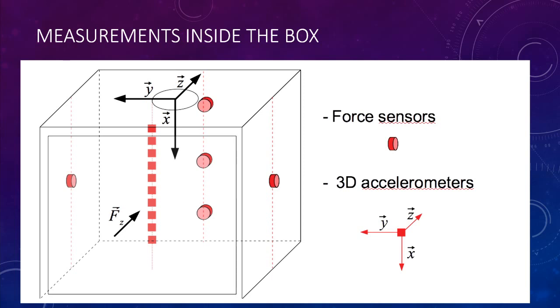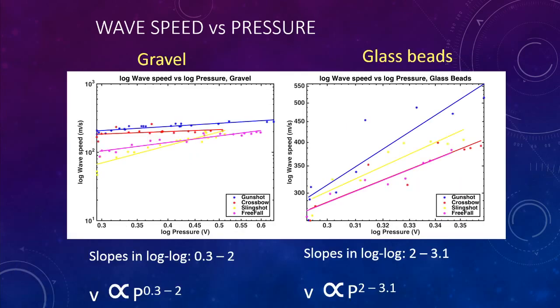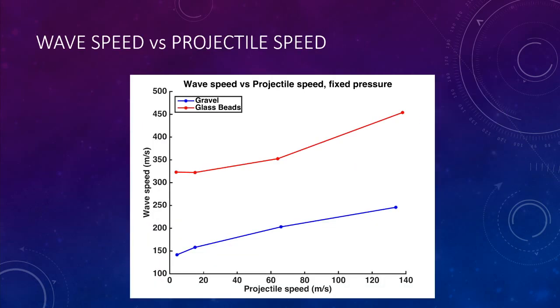Inside the box, we have a set of accelerometers and 4 sensors in the walls in order to know the pressure inside the media and the propagation of the wave. And this is the orientation of the accelerometers. Up to now, we have some experiments on gravel and glass beads, and you see here the dependence of the wave speed with the pressure. This is a very flat dependence, and in this case, we see a much steeper dependence, and one can compute the relation between the velocity and the pressure and these kinds of exponents that we get in one case and in the other. Also, we have some dependence of the wave speed with the projectile speed. So we see an increment of the wave speed with the projectile speed.